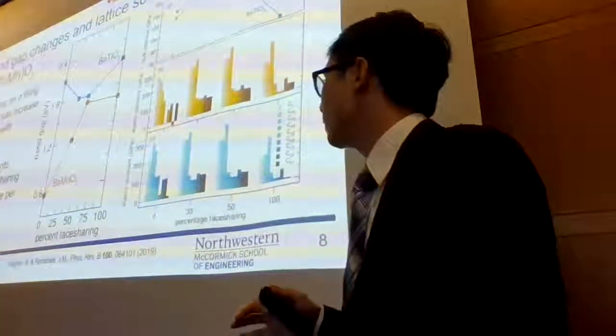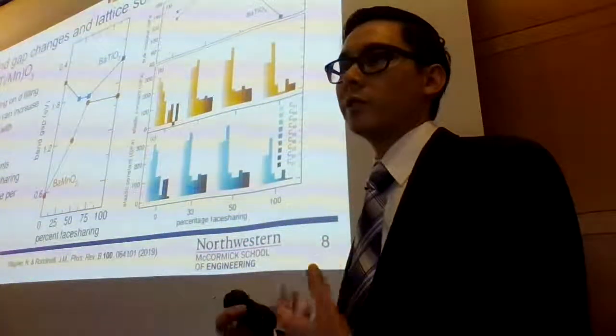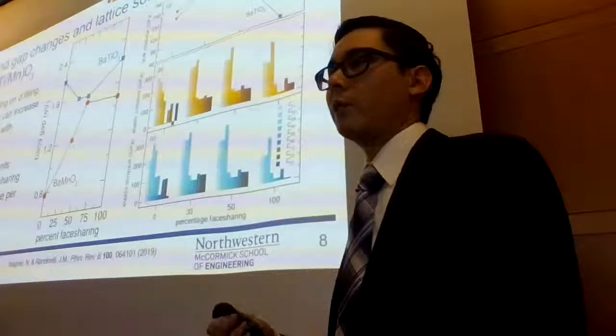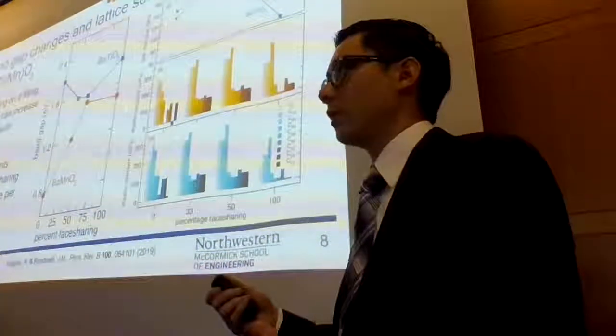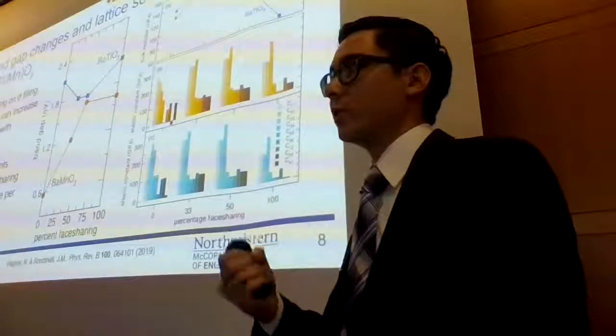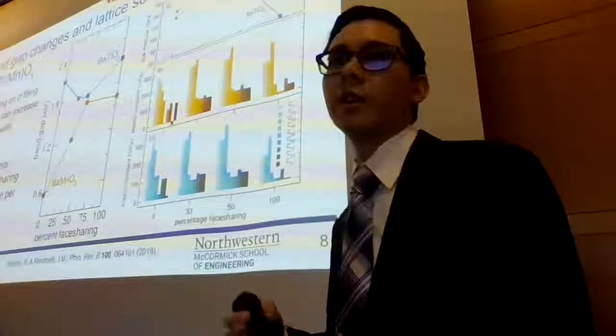And another interesting thing is we looked at the elastic properties of these materials. So you might expect that as you're switching from corner connected to face connected chains, you might expect some sort of stiffness along the chains relative to, say, a case where the octahedra are allowed to rotate around the corners.